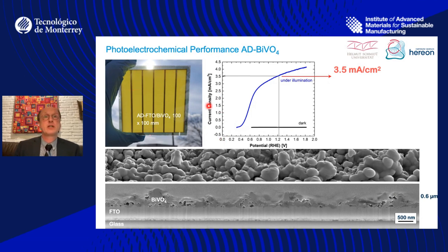And here you see what current density we get for different potentials. So this is basically the figure of merit, what we can achieve in hydrogen production. And you see the black line here is basically, if you don't shine any light on the surface, you don't get any photocurrent. As soon as light hits the surface and is absorbed, we get photocurrent, and the photocurrent is directly proportional to production of hydrogen.